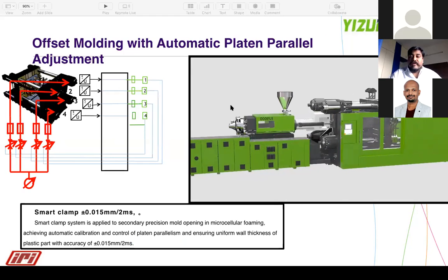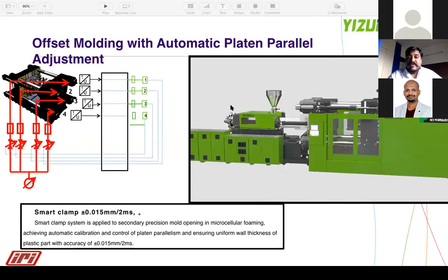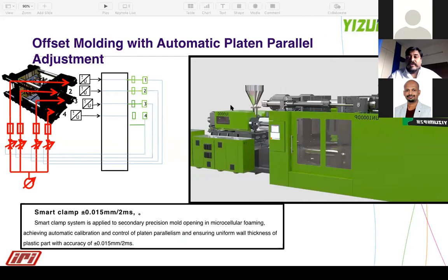Another very important application, which is possible only on a 2-platen machine, is when you are running an offset molding where the mold is not balanced. Then you have a clamping force variation on each tie bar differently. Whereas in a 2-platen machine, it is possible to adjust each of the tie bar positions to maintain uniform stress on all 4 tie bars as well as the platens. It is possible to automatically adjust the position of the tie bar so that the clamping force can adjust. It depends on the injection reaction force. Because of the offset molding, you have different forces. Maybe the left side has slightly higher forces than the right side. So accordingly, the clamping force can vary.